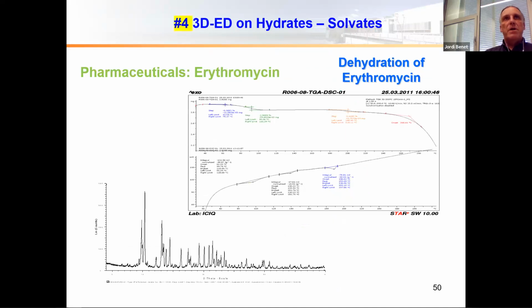I have a second example in relation to this. In this case, we are speaking about erythromycin. Erythromycin is a dihydrate, and here you can see the TGA and the DSC of this compound. And what you can see here is that it seems that the first water molecule leaves the molecule easily, and only the second water molecule goes with more difficulties, until finally we have melting or decomposition. So we probably have here a dihydrate.